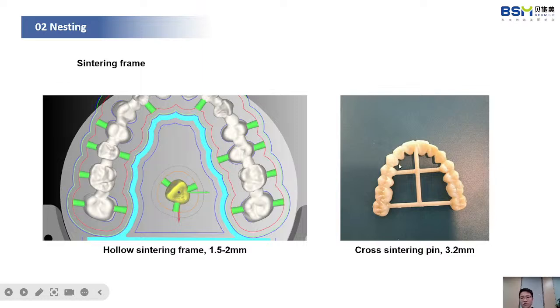And also we tested another type of the sintering frame. It's like this shape. For this kind of sintering frame, we add it in the designing software, not in the nesting software. For example, in the exocad, we can add some attachment like the round pin to the full arch, like this shape, the cross shape. And the diameter of the support pin is about 3.2 millimeters. And for this kind of sintering frame, some of our customers, our labs and our factories, we find it's very stable. So if you are interested, you can also have a try with this type of the sintering frame.